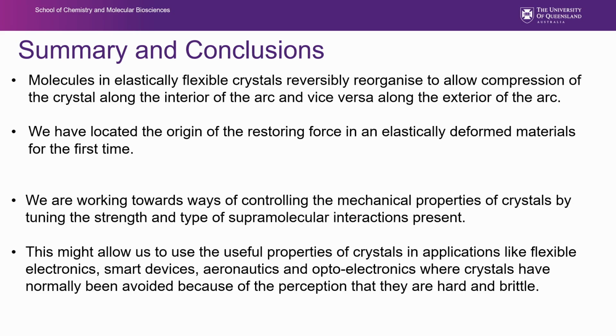So what do we know so far? Molecules in elastically flexible crystals, and this is probably every single crystal, we just haven't found the limits of where they are yet, reversibly reorganize in some way on the atomic scale to allow for compression and allow for expansion. So again, to get something that's elastically flexible, we fundamentally need to have that reorganization. We've located the origin of the restoring force in an elastically deformed material of any type for the first time. That is in the combination of intermolecular interactions. On the inside, it was stored mainly in the pi-pi interactions. On the outside, it was stored even in these weaker interactions.